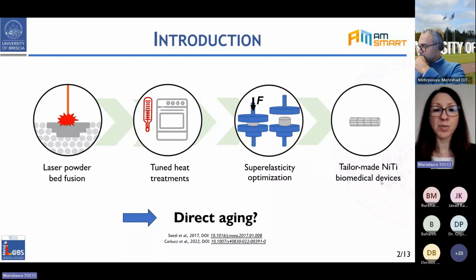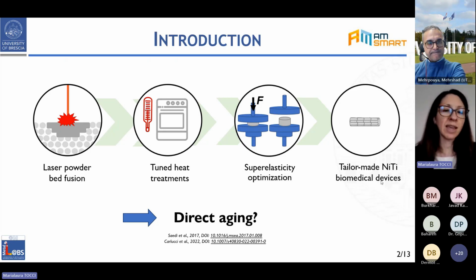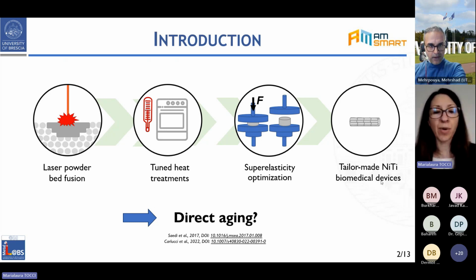But on the other hand, it is possible to exploit the microstructure that we obtain after the manufacturing process, so after the powder bed fusion, which we know is already a supersaturated solution due to the high cooling rates that we achieve during this process. So the question is, why not skip the solution treatment and apply aging directly after production, and see if we can tailor and achieve the superelastic behavior that we want. There are a few studies working on this topic, and therefore there's still work to do in order to understand if it is a feasible way or not to solve the problem.